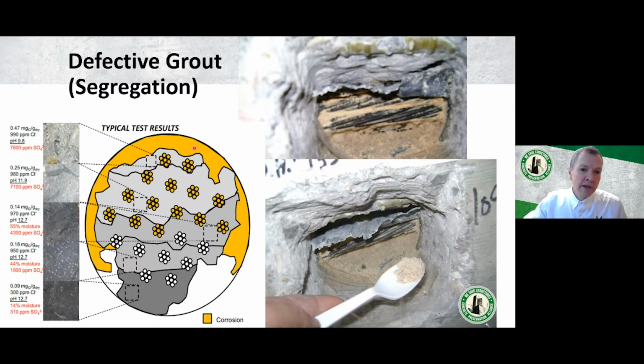You may not have any voids at all, but you'll have differences in material properties that can lead to corrosion. Generally the strands in the good quality grout at the bottom will be protected, and the strands in the lower quality grout that floats will typically corrode. One of the things that drives that corrosion is that where you have the higher water content grout, you tend to have a concentration of water soluble salts like chlorides and sulfates, and you'll end up having a corrosion cell, a concentration cell, where the strands in the higher sulfate and chloride content grout will corrode relative to where you have lower. And that's something that you should be aware of.